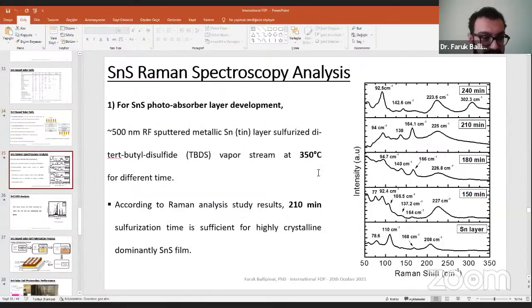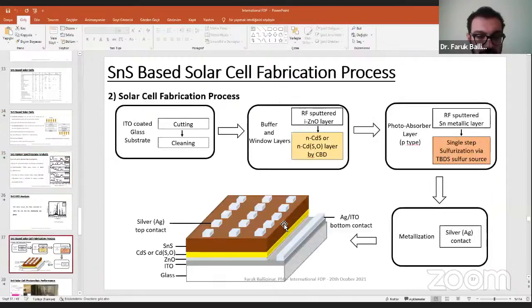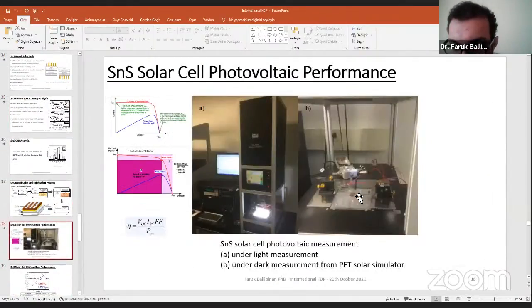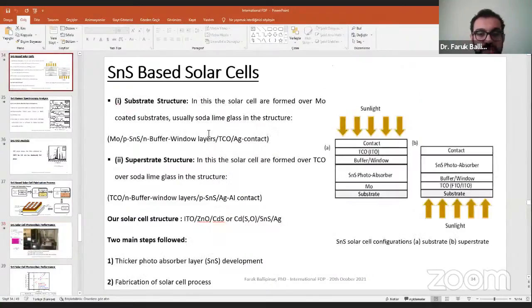So as we remember, this is our solar cell structure, and there is the real one in the solar simulator as well. We have only just TCO on the bottom and silver or gold on the top. That's it. But in this one, the moly sulfide is a major problem. So preferring the superstrate structure provides an opportunity to have higher efficiency compared to substrate.